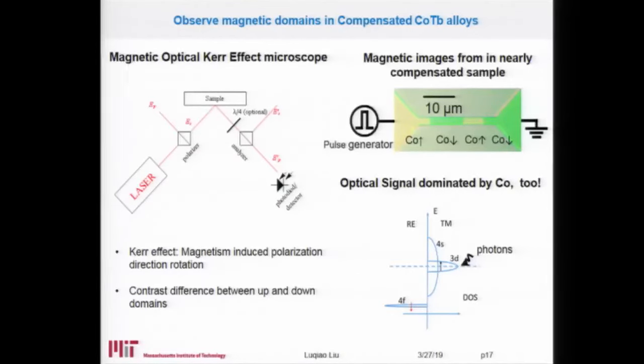The reason is that photon-spin interaction also has some selection rule. It's not integration over all of the spin states. It's only selectively sensitive to spin states located at a certain energy level. So that's why, when we measure the Kerr effect signal, we can still recognize those two different domains, although the net moment is very close to zero.